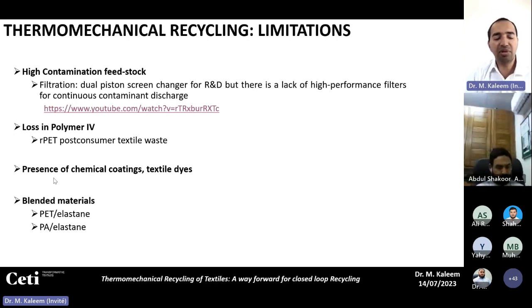when you recycle used textiles, they may contain different dyes and coatings. For example, you apply a spin finish over the filaments. If the percentage of these colors and coatings is so high, that can cause recycling processing problems. Also, if you want to develop a textile from black feedstock and you want to get a white one, you cannot get it through the thermomechanical process. If you put in black, you will get black at the end. So we are limited here by the colors, right?